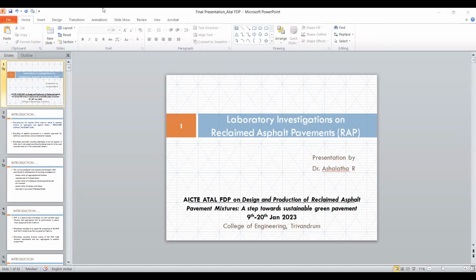Right. So these warm mix additives started being used, and again there are many families of warm mix additives. Each additive works in a completely different way. In fact, what ma'am explained now is to reduce the viscosity of the binder in the mixing and compaction regime. But there is one small issue with the Sasobit. What will really happen around 80 or 90 degrees centigrade as the temperature comes down, it starts crystallizing and it tries to give some additional rut resistance because it makes the binder stiffer at 60 degrees centigrade. And then if you go all the way down to 20 degrees centigrade, what can happen is the material's fatigue failure also becomes a critical issue.